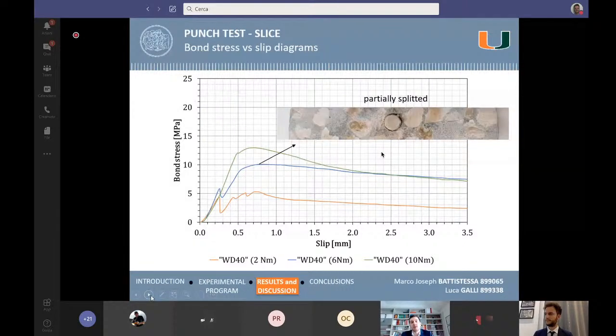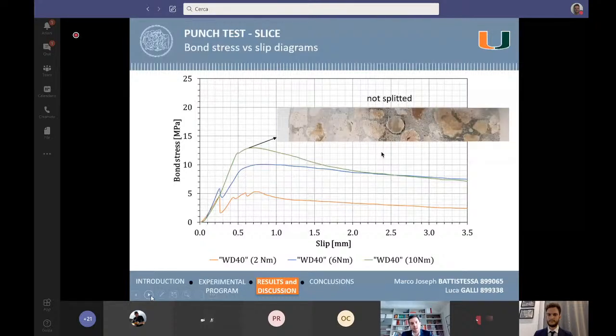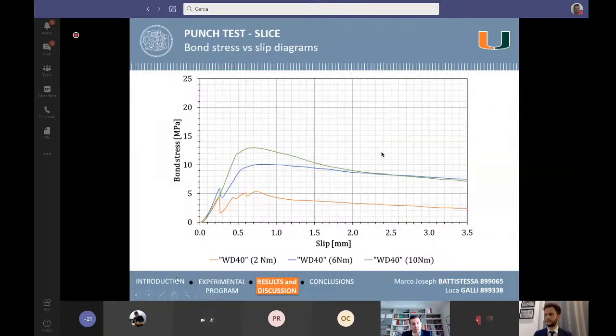The blue line instead shows us the specimens recorded as partially splitted, where a slight crack on the bottom surface of the slices was recorded. The green line will explain the typical trend in which no evidence of concrete splitting was recorded. In the first two cases, we can see that an initial discontinuity arises in bond stress values around 4 or 5 megapascal. In this range, the average tensile strength of the concrete, which was estimated equal to 3.5 megapascal, might be reached. So the presence of this discontinuity seems to be related to the concrete cracking.